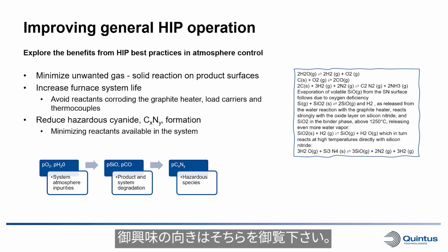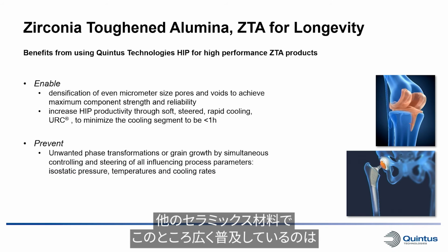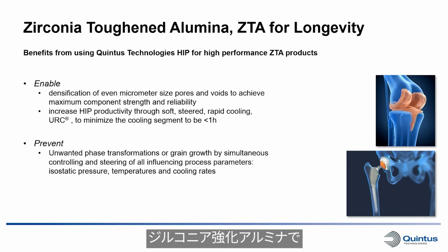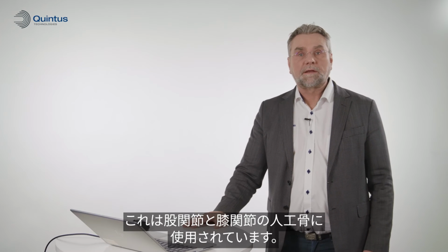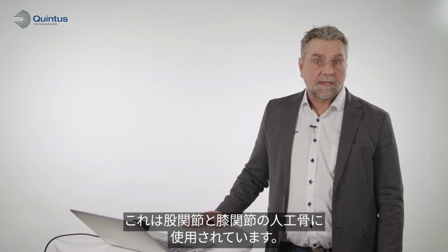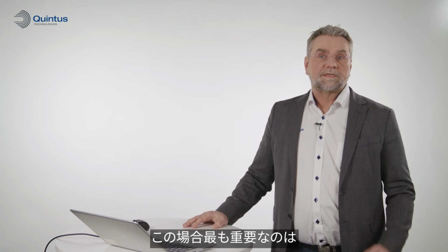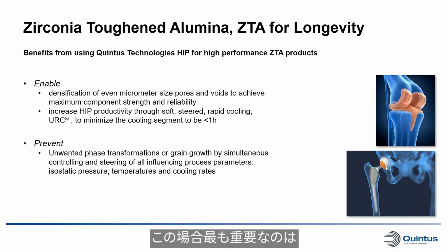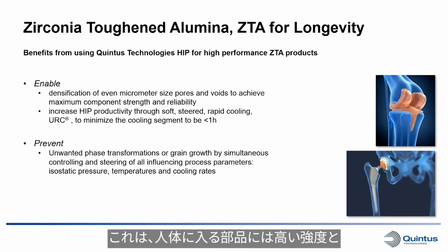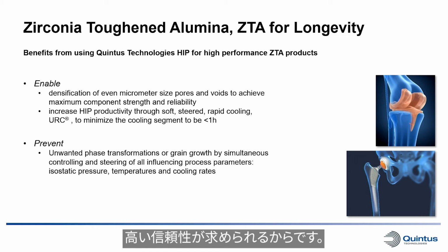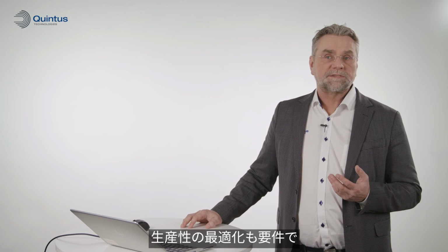The other ceramic system very much popular at the moment is the zirconia toughened alumina, used for medical implants for our hip and knee joints. In this case, of course, the first thing is that we want to make sure that we densify the pores and voids. We need high strength and we need high reliability for components going into our body. We also, when the volumes now are increasing, need to make sure that we optimize the productivity.